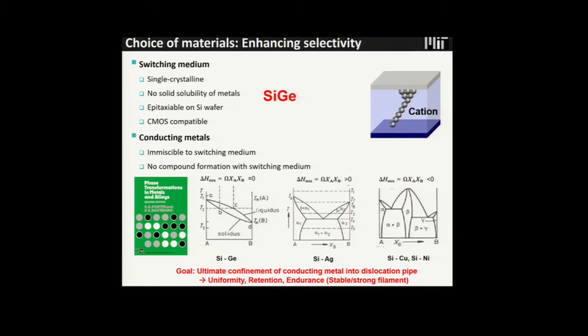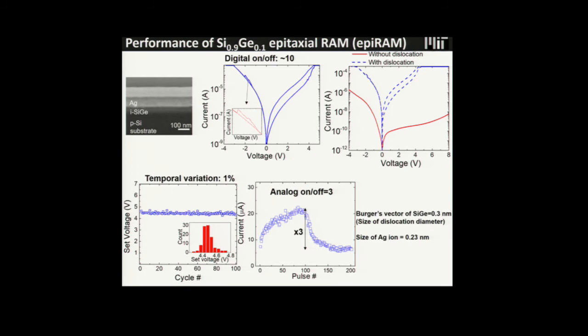So what's perfect? We went through all the phase diagrams. Then silver was the perfect and right choice because it's immiscible. Silver doesn't want to be mixed into silicon. So we picked silver as a cation. Then we fabricated the device. Then we have excellent, very robust switching behavior. Without dislocation, by just growing intrinsic silicon on a P plus silicon wafer, you don't have a switch. You really need a dislocation to switch this device.